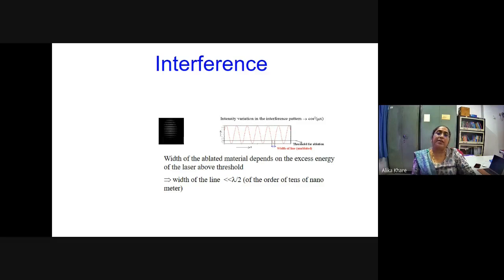Now, if we illuminate the thin film or surface on which we want to do the writing with this kind of interference pattern, and suppose the threshold for ablation is this solid line, what will happen is that material in the region where intensity is much larger than the threshold will get ablated, leaving the bottom region unaffected. In this way, one can have a pattern of size much less than lambda by 2. The periodicity is limited by lambda by 2, but the structure size will be much less than that.